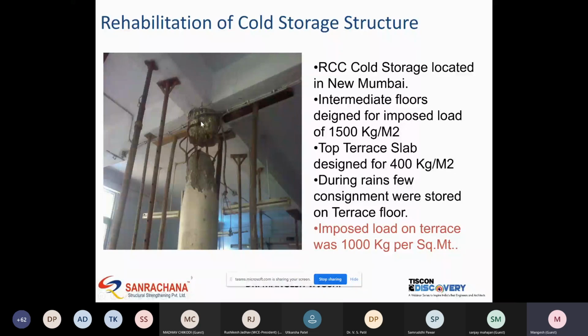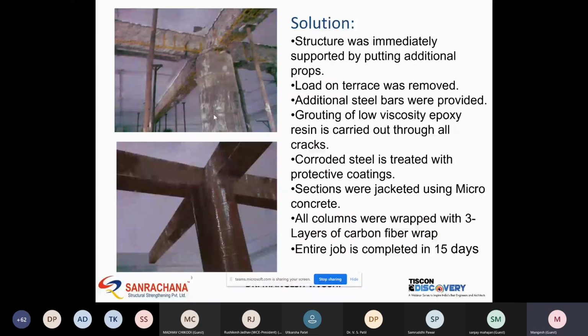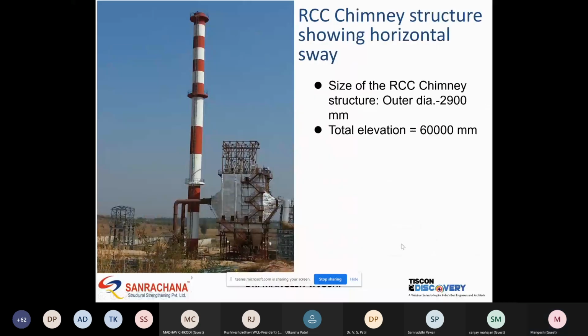So this was the solution. The structure was immediately supported by putting additional props. Load on the terrace was removed. Additional steel bars were provided. Grouting of low viscosity epoxy was carried out. Corroded steel was treated with protective coating. Sections were jacketed using micro concrete, and all columns were wrapped with 3 layers of carbon fiber wrap. So the entire job was completed in 15 days.